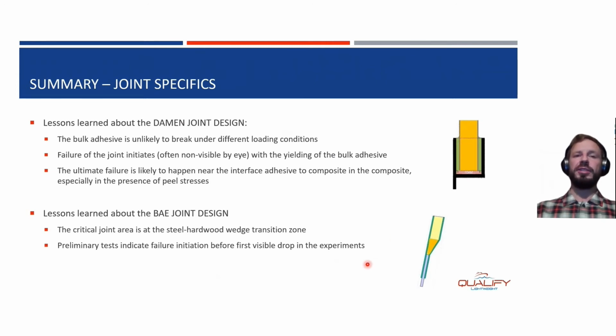What we learned of the BAE joint design, the critical load area is the steel hardwood wedge transition zone, so that area here. And preliminary tests indicated that the failure initiation took place already before the first visible drop in the experiments. So that means we have already a failure initiation without any loss of joint stiffness, joint integrity.